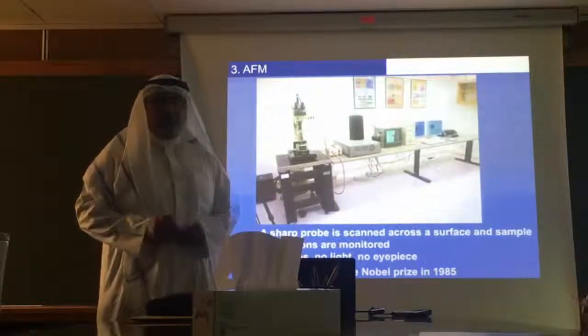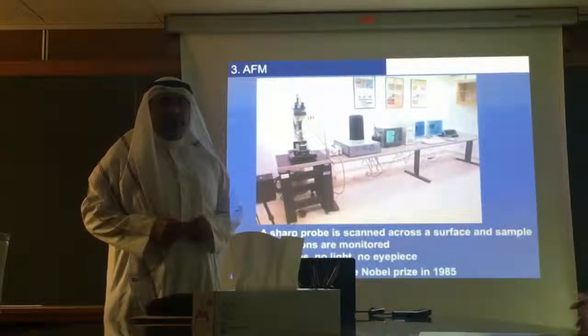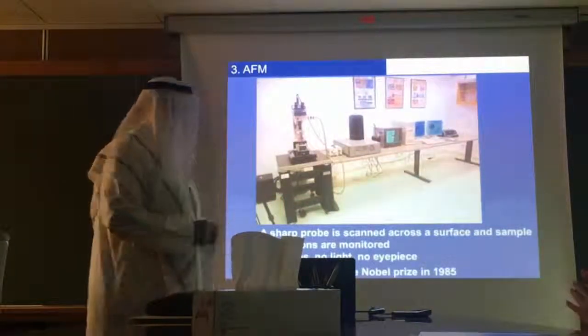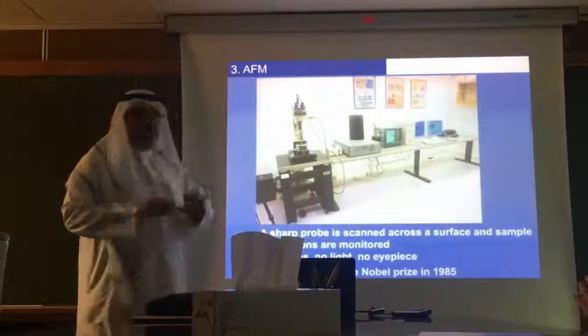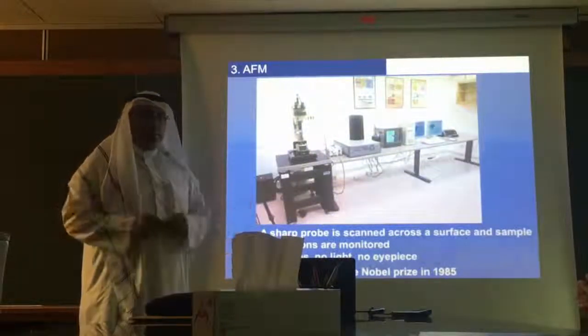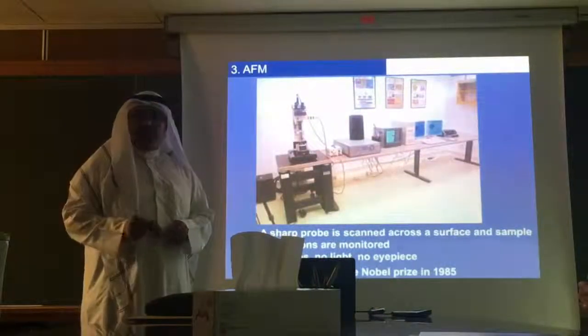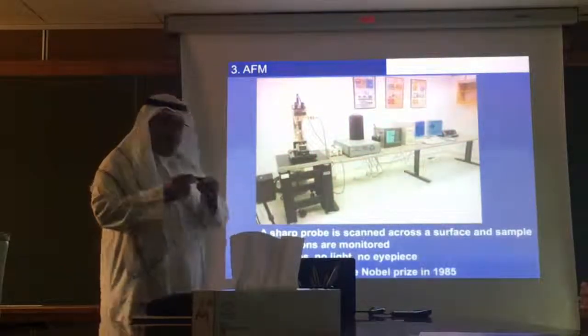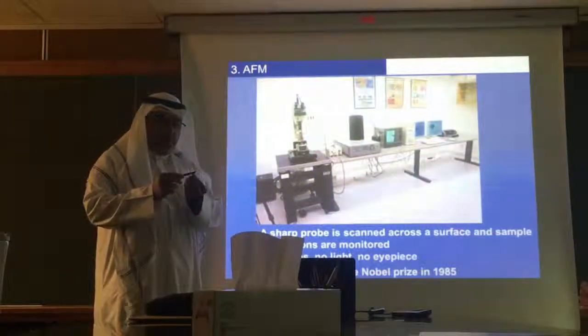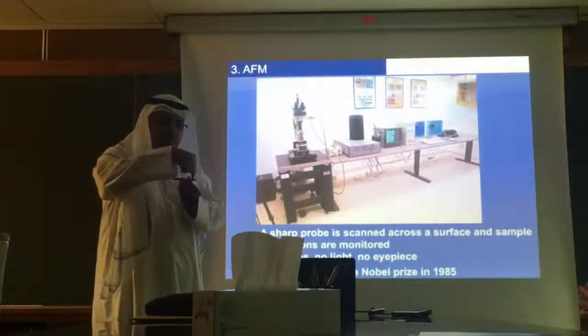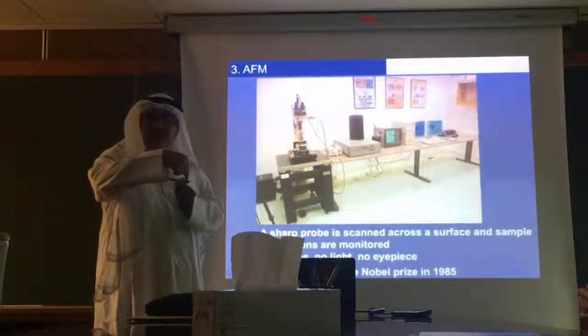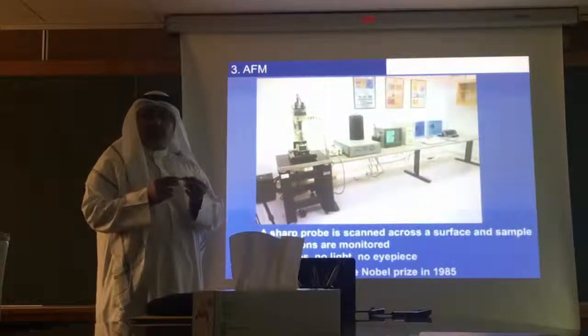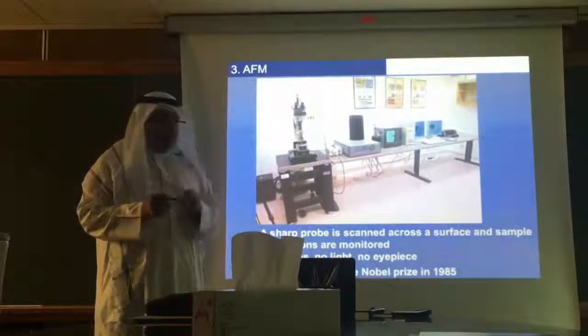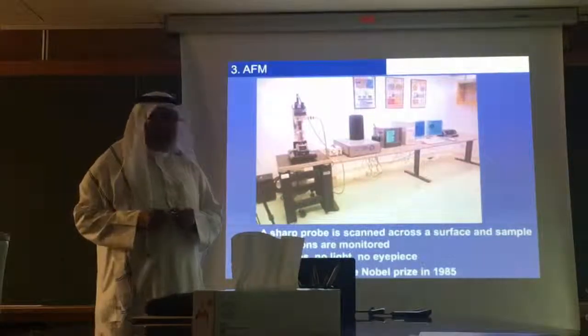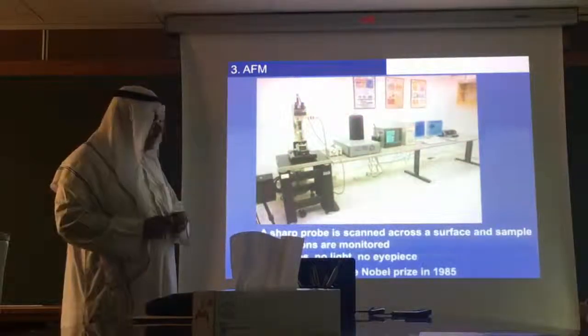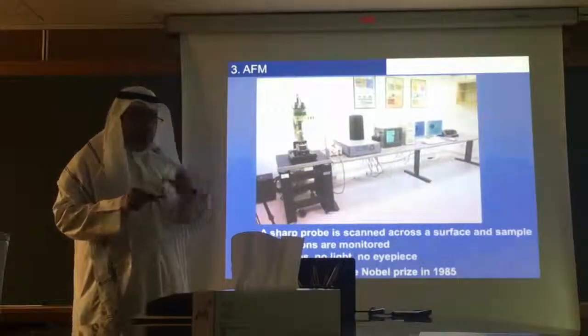Now there is another technique called AFM. This is also very excellent for nanotechnology. The main advantage of this device is that we don't need the vacuum anymore. No need for the vacuum, because I'm not going to bombard my sample with electrons. I'm going only to use a cantilever with a very sharp tip, and then I shine a laser on top of the cantilever, and the cantilever is made from a material excellent in reflecting the laser. Usually, I think it's silicon carbide or silicon nitride, which is excellent for reflecting the laser.